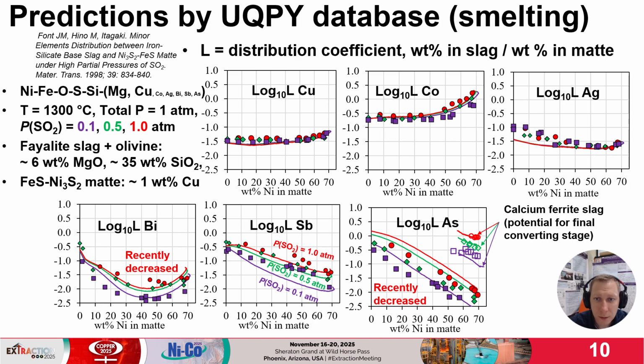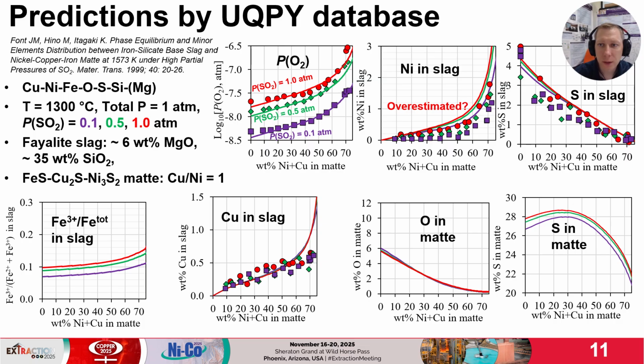For comparison, the distribution coefficient of arsenic using calcium ferrite slag chemistry is also provided. They might have applications during the converting to control the partitioning of arsenic into matte, but they also dissolve high concentrations of nickel. Previous slides were for nickel-based mattes with low concentrations of copper. The same authors also had a study for high copper mattes with copper to nickel ratio of 1. The model works reasonably well, but the concentrations of nickel in slag seems to be overestimated.